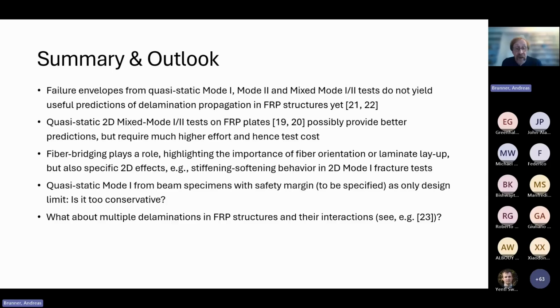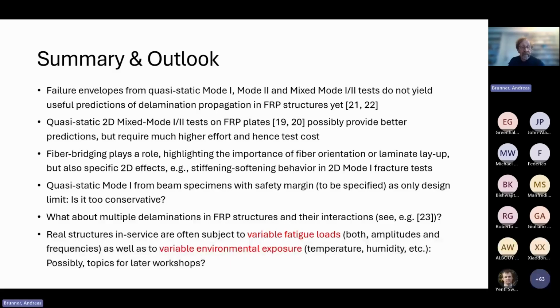But then on the other hand, and this has not been discussed in much detail yet, in typical fiber-reinforced structures you don't have a single delamination. You have multiple delaminations in different planes, and depending on how many there are, their shape, size, etc., you will run into interactions between these. And then the quantification of the toughness becomes extremely difficult. And then, of course, also the question is, are quasi-static tests sufficient? Because the real service loads are typically variable fatigue loads, both with respect to amplitudes and frequency, including also variable environmental exposure, varying temperature, humidity, etc. And that also will have a big effect.